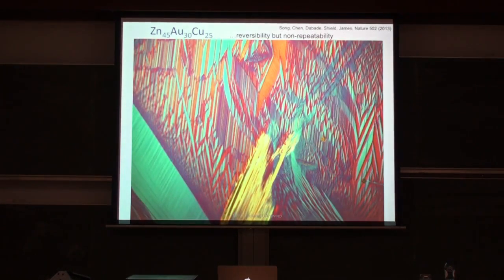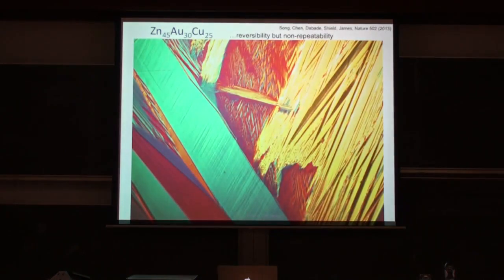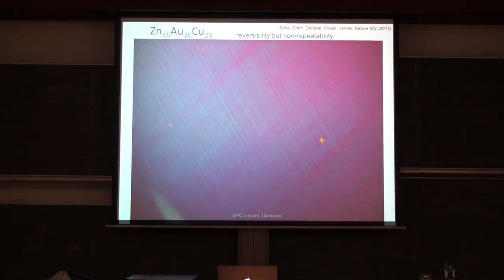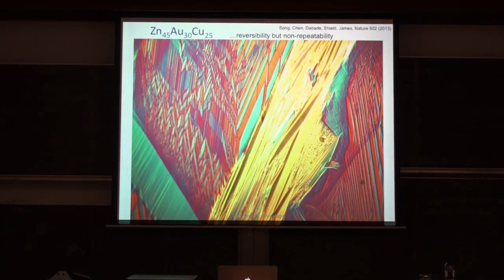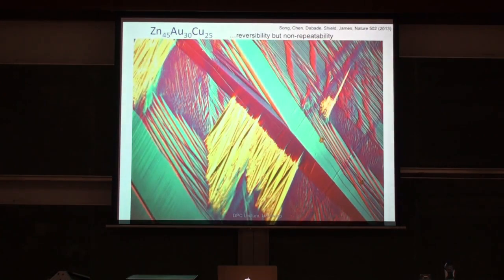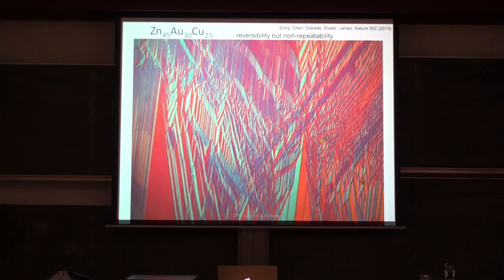Again, many things I could tell you about this picture, these pictures are completely different from what they expect. And so it seems that there's quite a strong effect of satisfying these cofactor conditions on the behavior of the material. Now, we saw that it had low hysteresis. We said, what about the reversibility with cycling? So we put it in a cycling machine, like this kind of machine, and we cycled it. Of course, I'm a theoretician, so my lab can't do very sophisticated things. So we did 20,000 cycles.